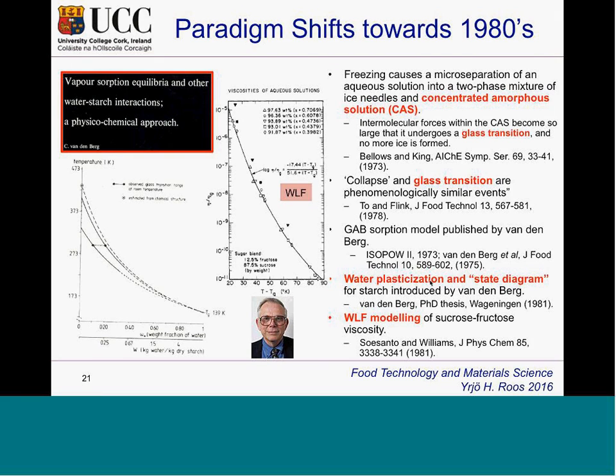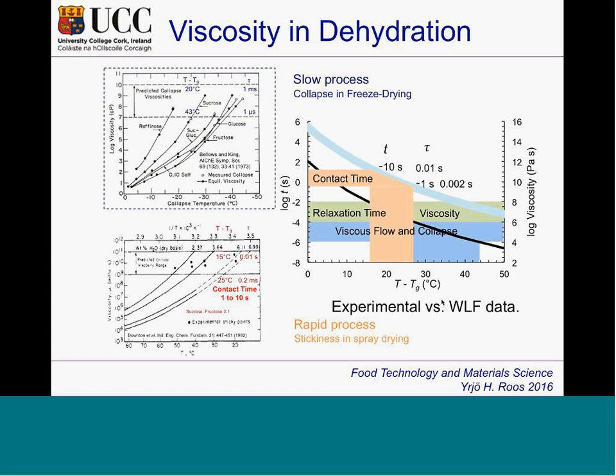These were all behind the Williams work by Harry Slade. We have actually analyzed quite a lot of these data from viscosity measurements, etc., which are extremely time-consuming. What we have been able to explain is that if you look at the relaxation time above the glass transition, you would find that the viscosity or relaxation time has a critical value for contact in spray drying, where time needs to be allowed for particles to flow before they adhere to surfaces.